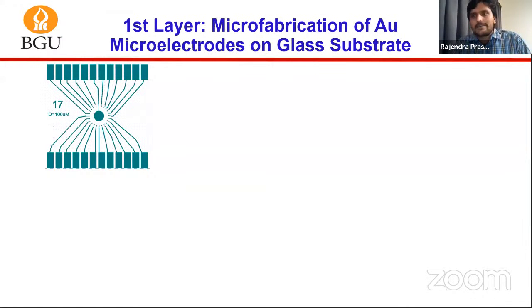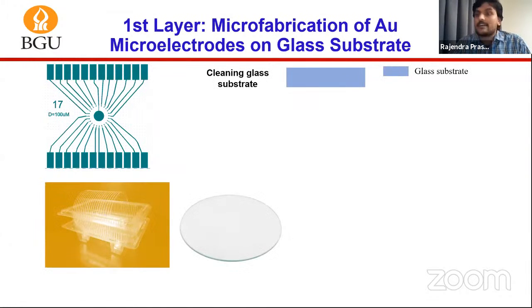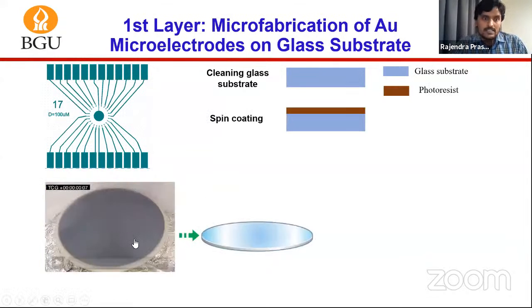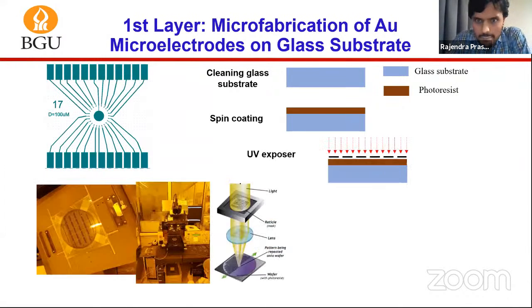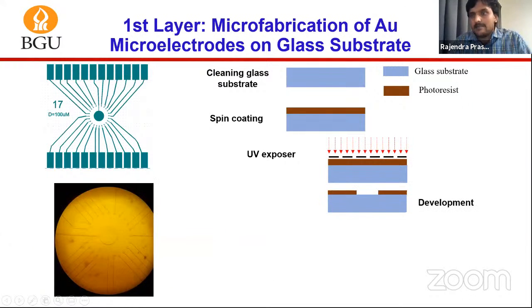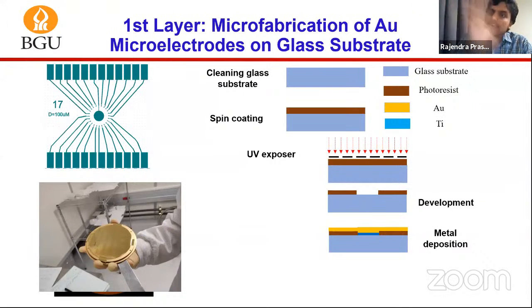In order to microfabricate the first layer, which is made of gold microelectrodes, we started with cleaning of the substrate, which is a 4-inch glass wafer. Then we spin coated a photoresist, a photosensitive material, onto it. After that, we patterned it using our mask that you can see here, and exposed it to UV light. By development in a certain solution, we got this photoresist pattern. Then we deposited titanium and gold on it. The titanium is a very thin layer which is used for adhesion between the gold and the substrate.